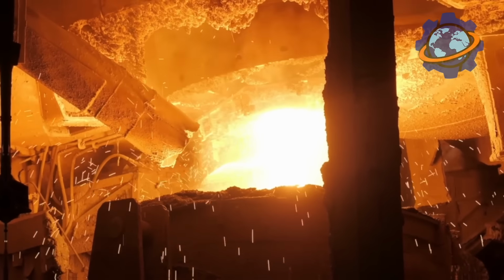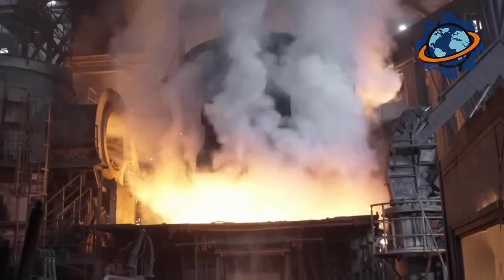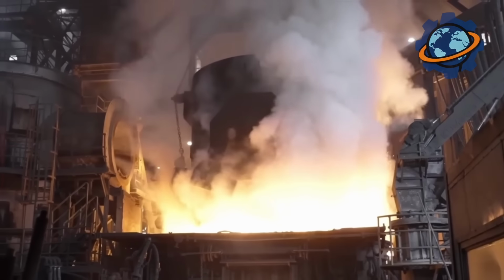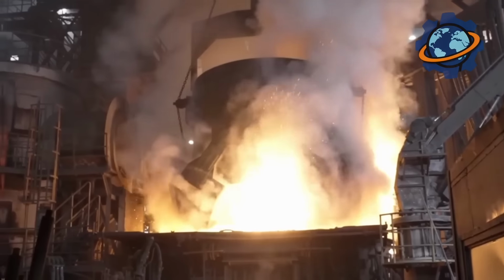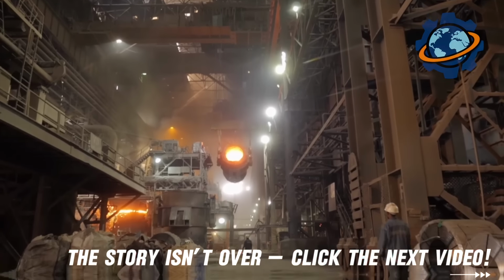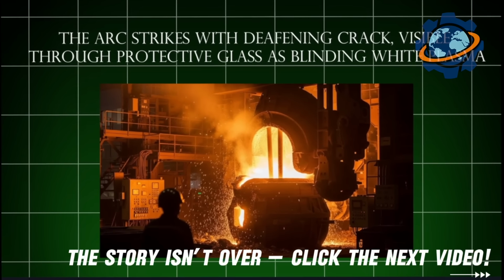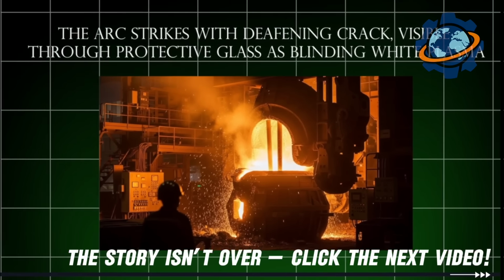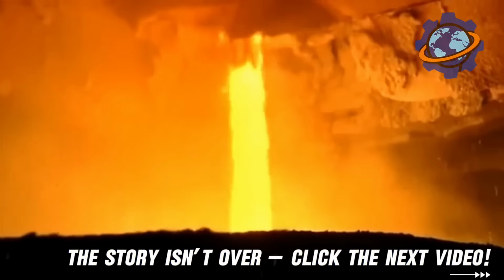The initial charge contains 200 tons of scrap steel loaded via overhead buckets. Operators lower electrodes carefully. Too fast, they shatter. Too slow, productivity suffers. The arc strikes with a deafening crack. Visible through protective glass is blinding white plasma. Metal begins melting immediately. The sound evolves from cracking to roaring as a molten pool forms.